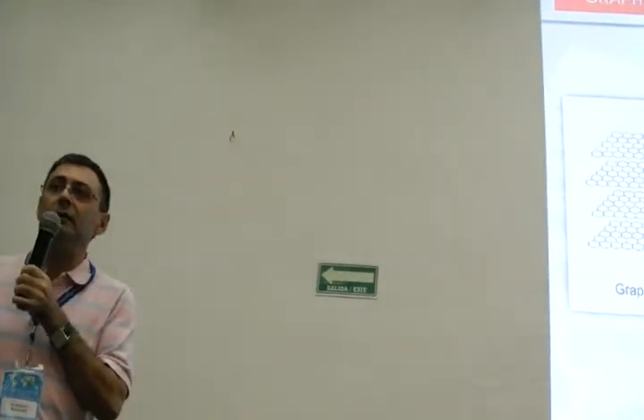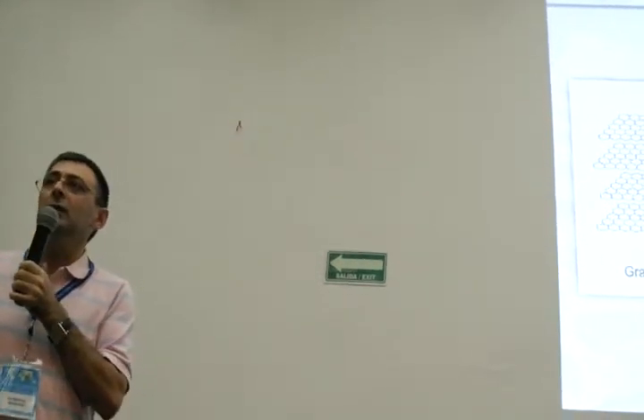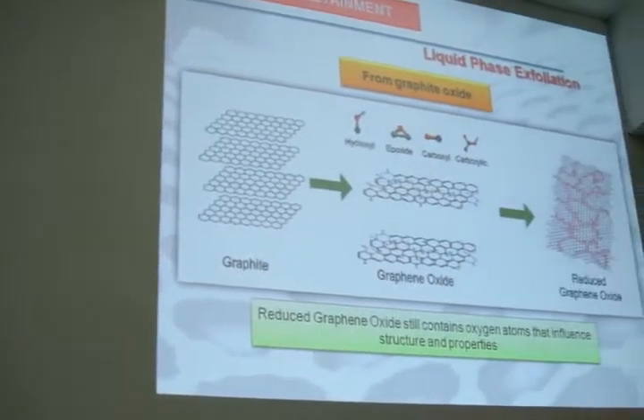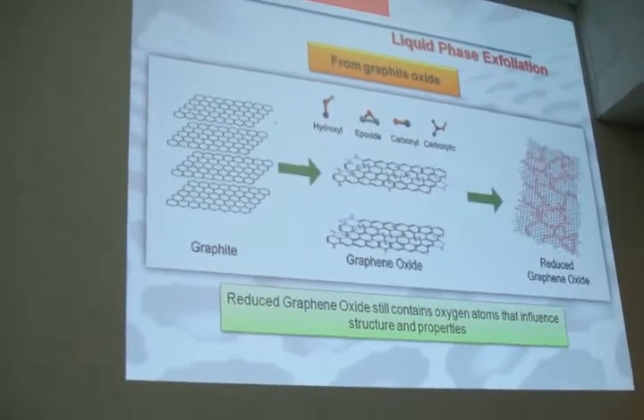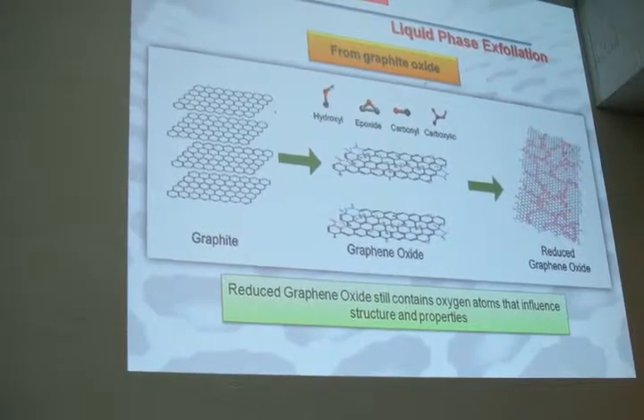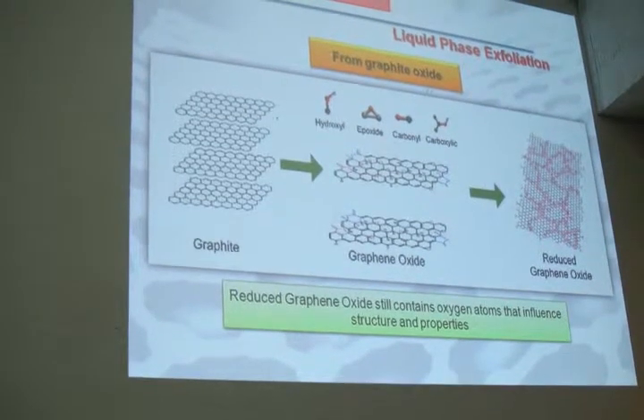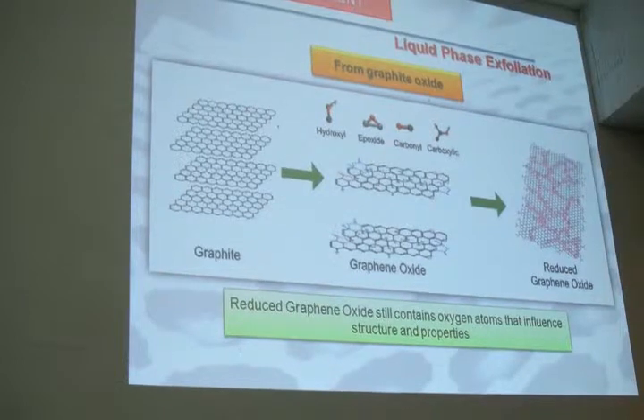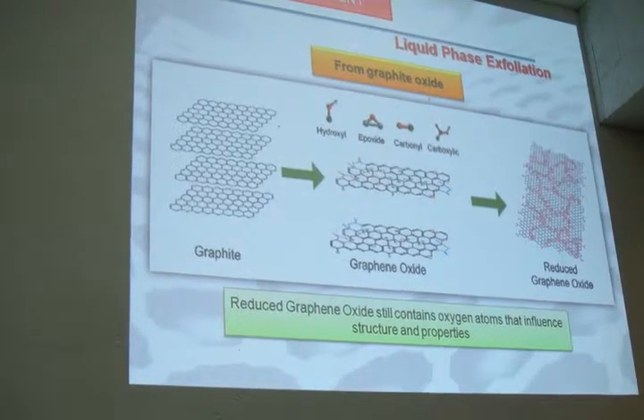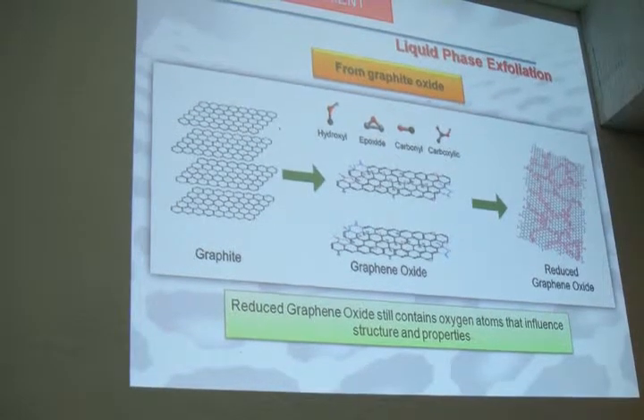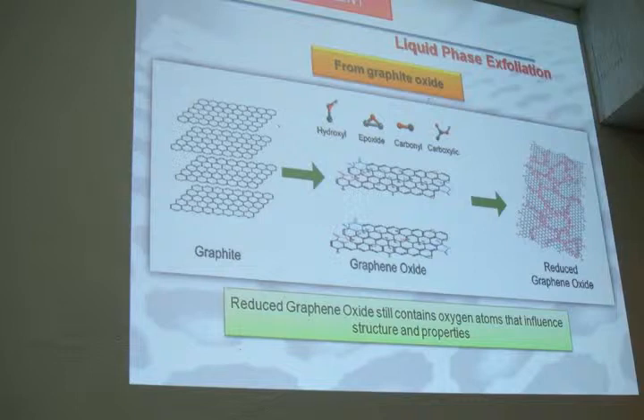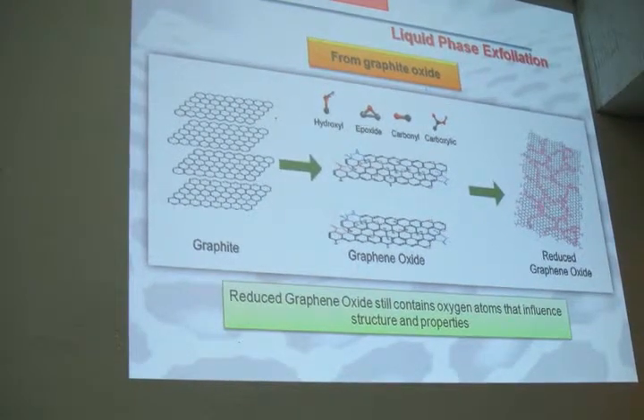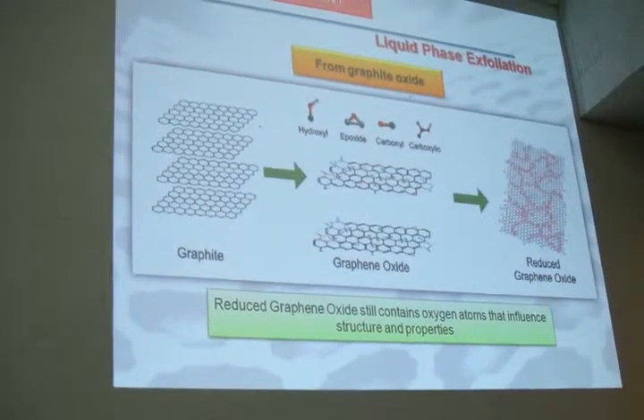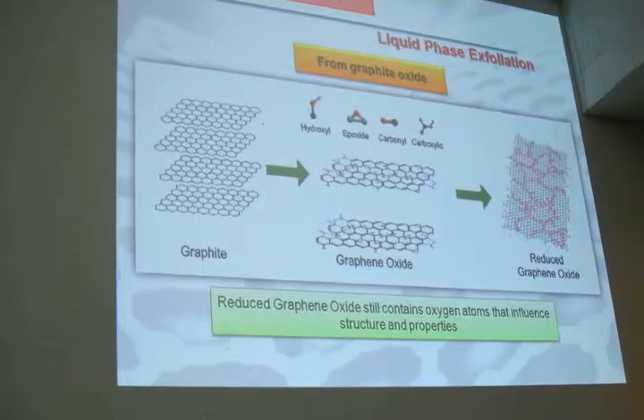However, graphite oxide is so polar that it can be dissolved in some polar media by sonication, for example. So from graphite oxide, you can have graphene oxide after exfoliation. And if you reduce graphene oxide, you obtain something else. What? Some people, most people, call it graphene. But it's not. Why not? Because there are a huge number of oxygen-containing groups, and so we can call it reduced graphene oxide, but not graphene.